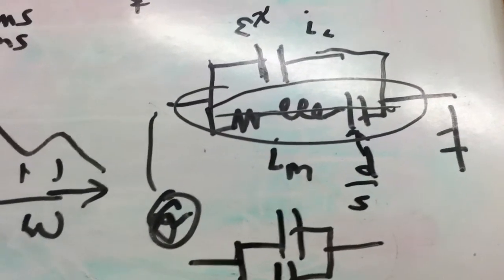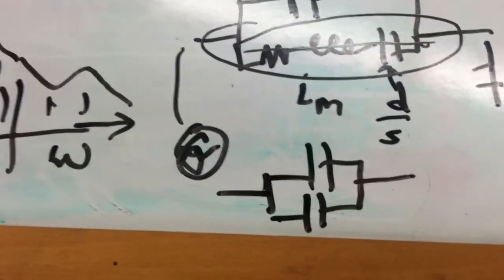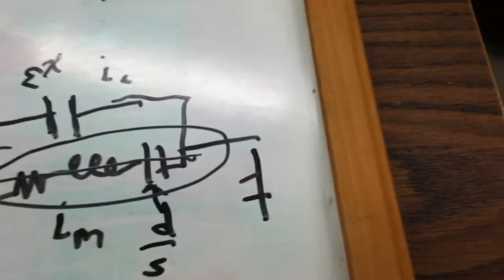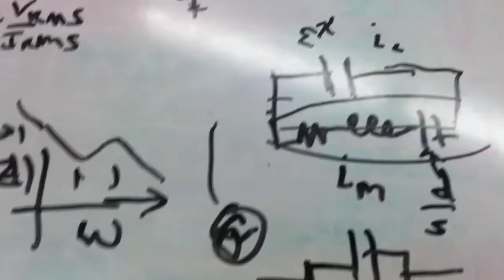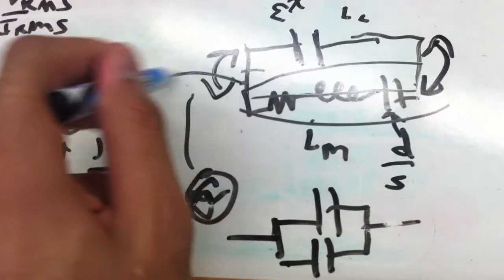But at the anti-resonance, what happens? Well, there are two explanations I'm going to give you. The first explanation is that this forms a resonance circuit here, an anti-resonance circuit, where the current is being exchanged between this capacitor and this LCR circuit. The current is being exchanged, and it's not being leaked outward. So the current is not flowing out of the system, it's just flowing in a loop.